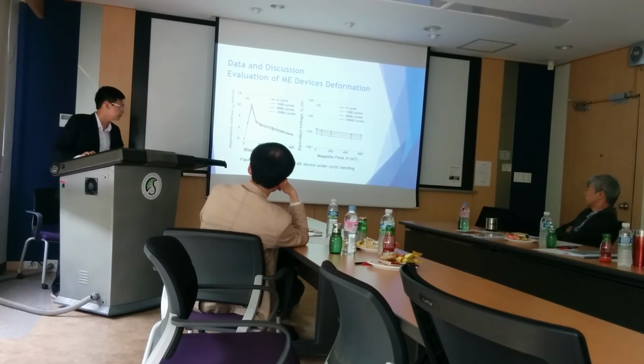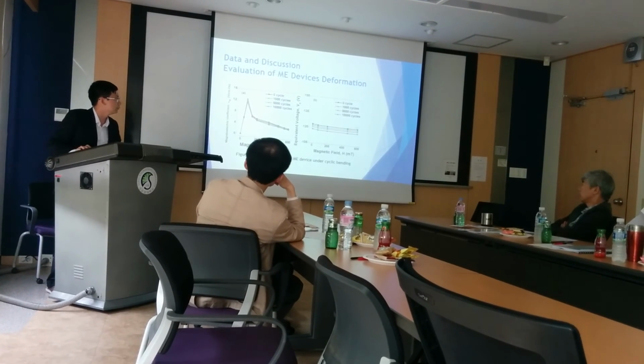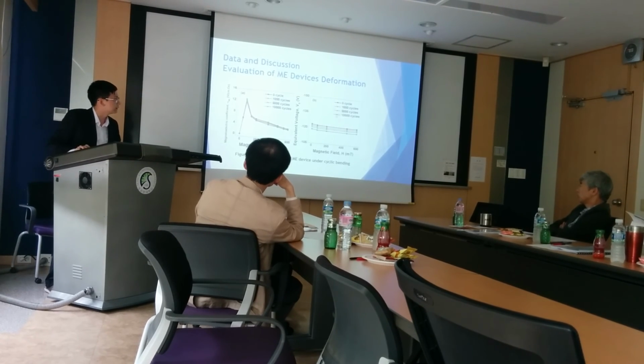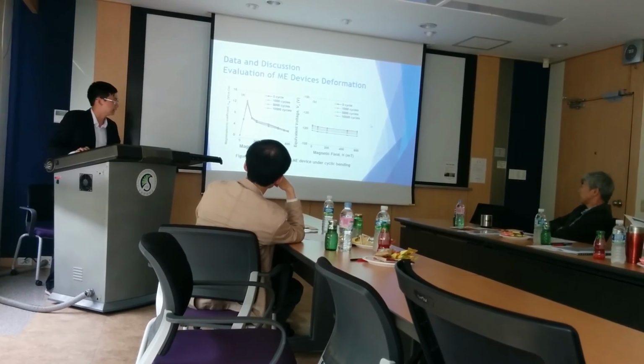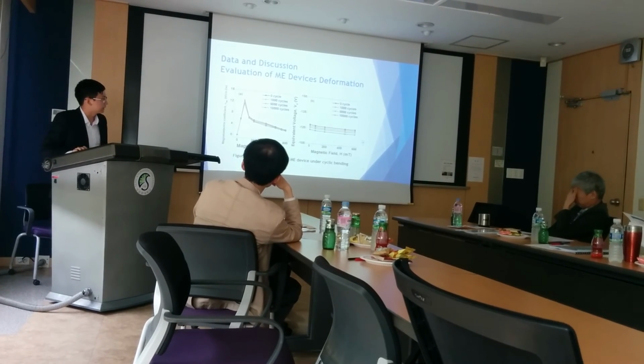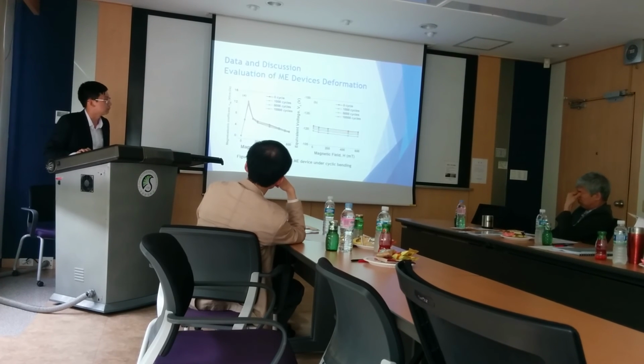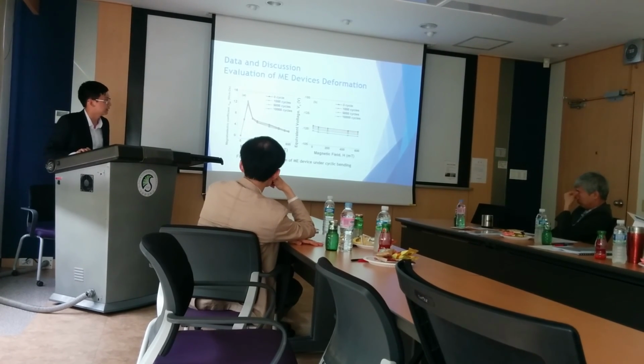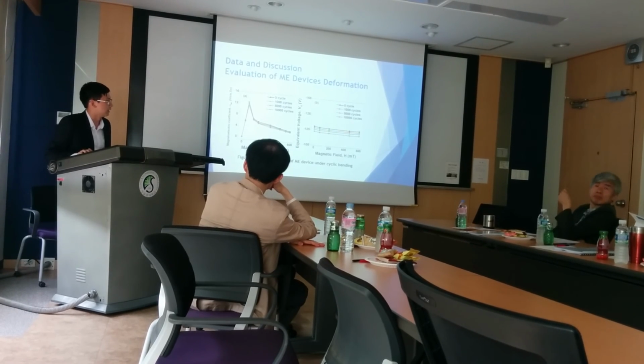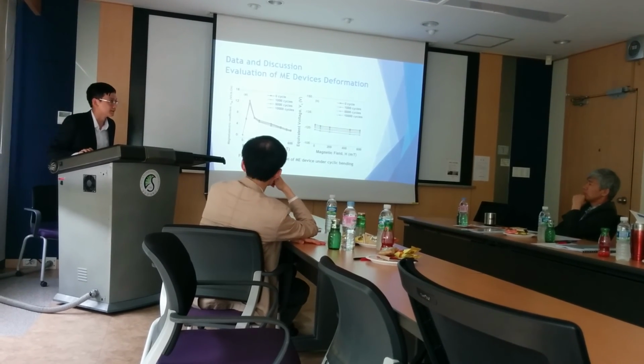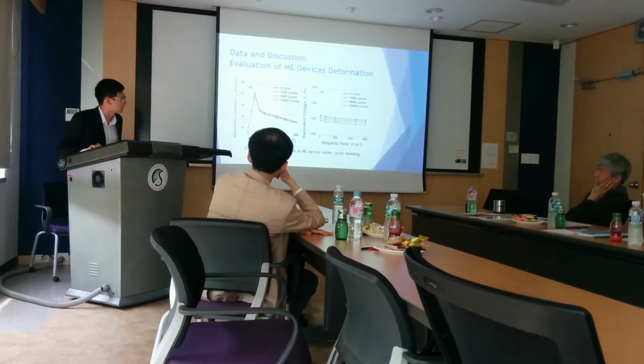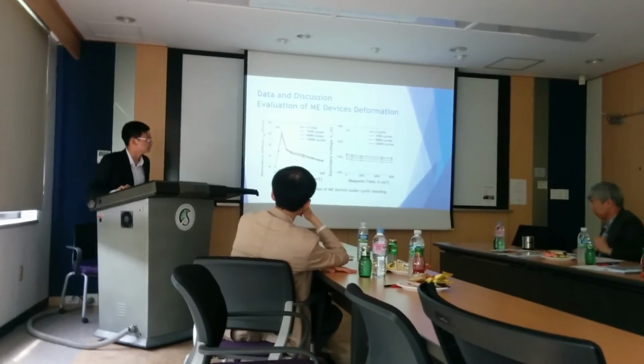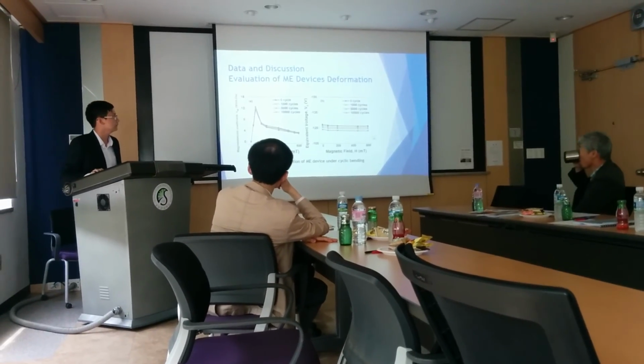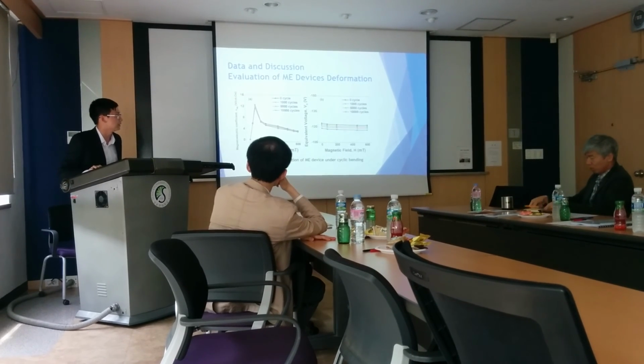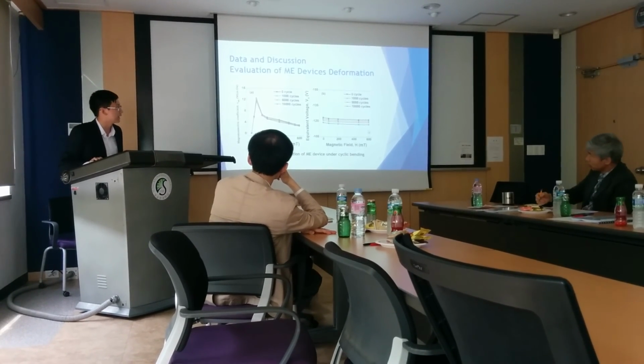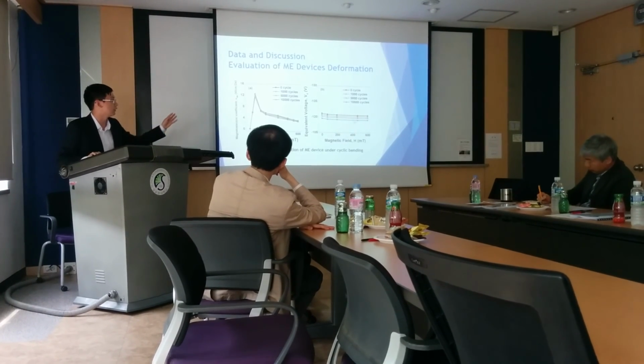Then we see that the equivalent voltage decreases when we do the cyclic bending more times. I believe that when we do more cyclic bending, the CFO layer will have fewer domains, and then it will reduce the polarization of the PVDF-TrFE. So you can see that the equivalent voltage of the PVDF-TrFE is slightly reduced. However, we can assume that our device is stable because the change is very small.